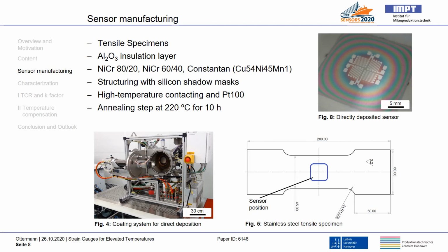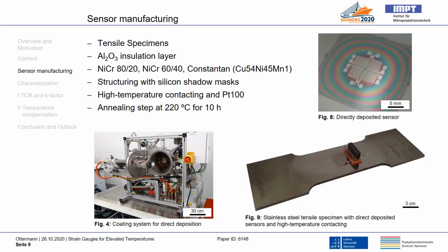The design consists of 2 half bridges with 6 contact pads each. This enables the 4-wire resistance measurement of the single strain gauges and the 5-wire measurement method for the half bridges. Now the pads are connected with conductive silver adhesive to a special circuit board which is designed for high temperatures. A PT100 temperature sensor is added in order to measure the temperature during the characterization process. The last step is an annealing step at 220 degrees Celsius for 10 hours in order to stabilize the resistance values.